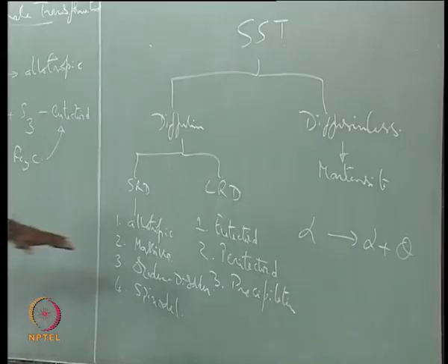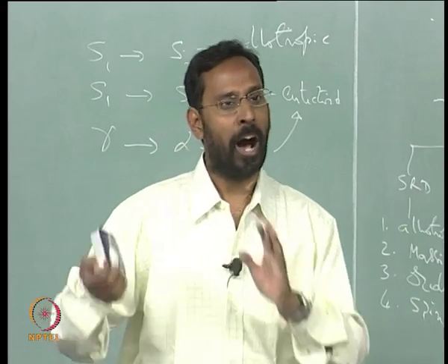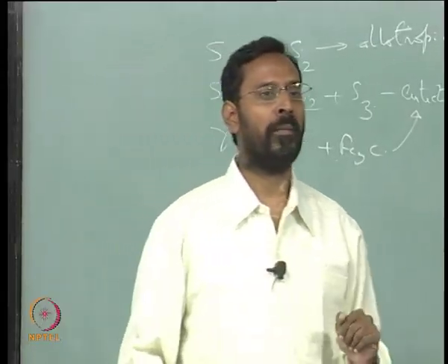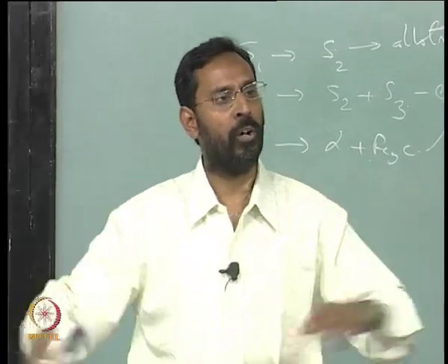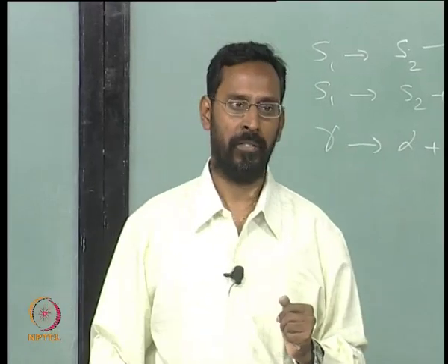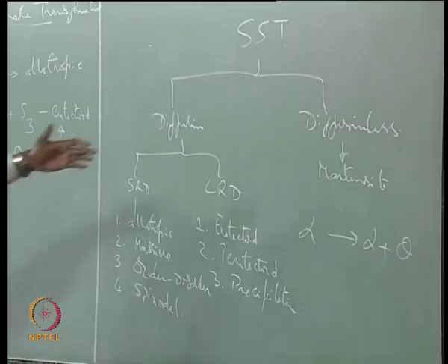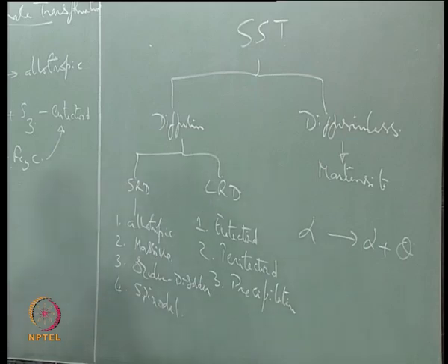So that is all the precipitation. Martensite, which is, let us say, a body centered tetragonal structure, gives you BCC alpha plus the epsilon carbide, which is hexagonal, and then this epsilon carbide, as it grows slowly, becomes orthorhombic cementite. The same thing happens even in aluminum copper. We are going to see now that it first gives you GP zones, and then slowly it gives you theta double prime and theta prime, and finally the theta. We will see why this sequence has to be maintained.